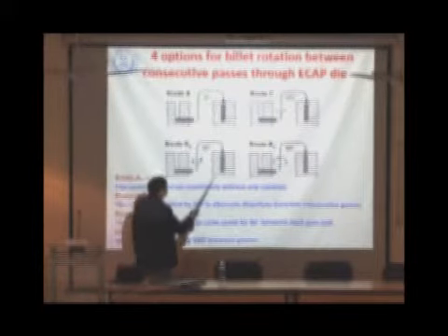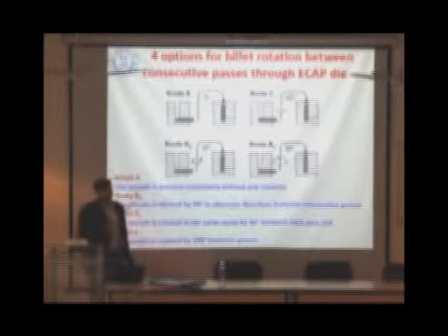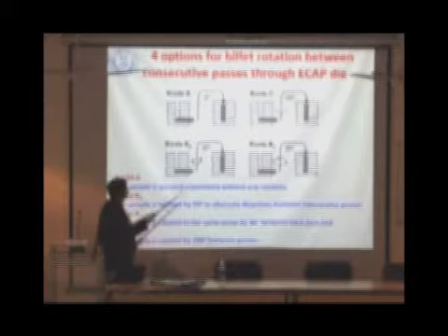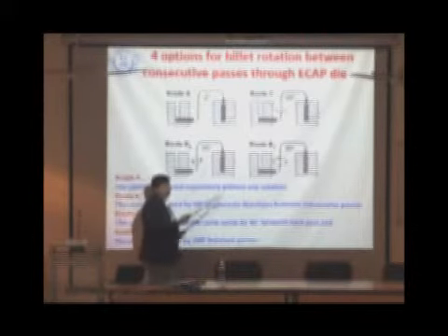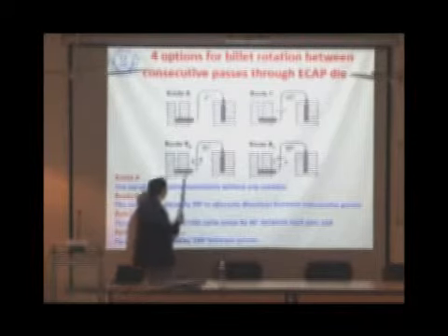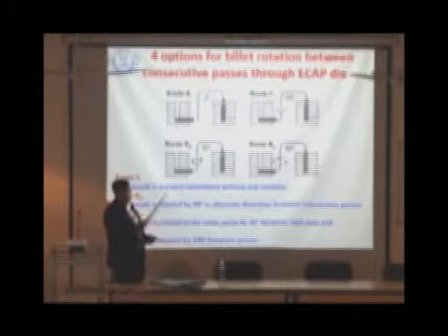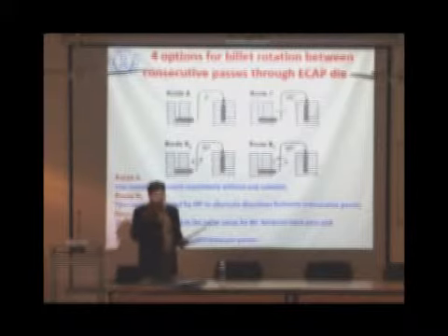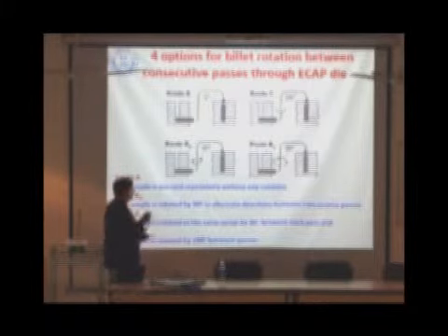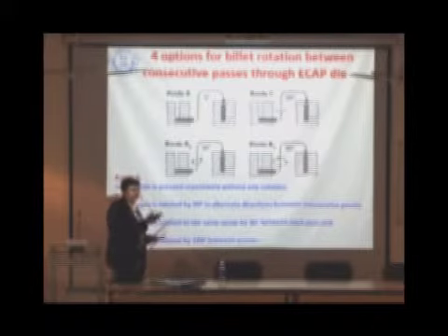The problem with this process is we cannot get uniform strain in one pass. We have to do one pass, then again put the billet again, then again one more pass, then rotate the billet, then again one more pass. So we have different routes to cover the entire microstructure of the billet. It becomes a very complex and time consuming process, so the problem comes with commercial viability.